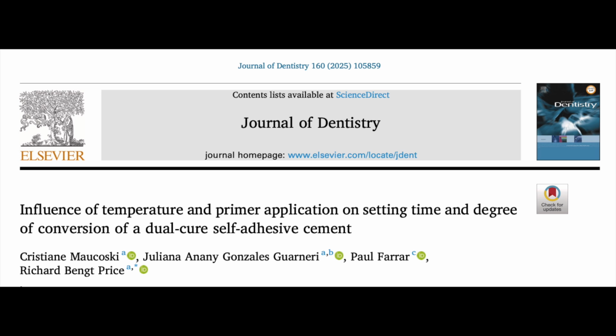Okay, so setting time is influenced by temp and primer. What about the degree of conversion, the DC? Yes, DC. So this is basically a measure of how completely the cement polymerizes, how complete that chemical reaction is. And higher DC generally means a better, stronger, more stable material long-term in the mouth. Precisely. And here, the primer was really the star. The most dominant factor. According to this study, yes, applying the primer had the biggest positive impact on achieving a higher final DC. Temperature played a role too, though.